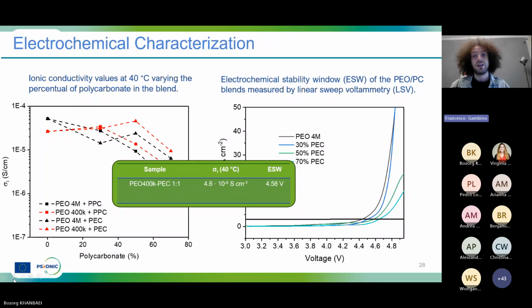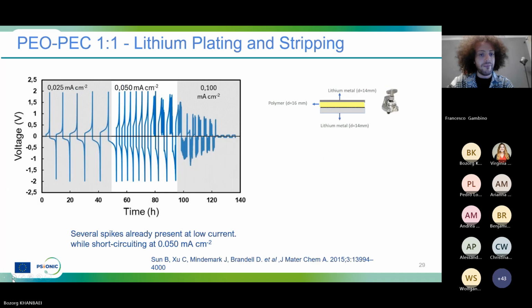At this point, we selected one membrane to further characterize, and in this case, we selected the one made of PEO 400,000 mixed with PEC in the ratio 1:1, because it displayed the best ionic conductivity among the series, and also the electrochemical stability was improved compared to the starting material. Next slide. We started the characterization of this membrane with lithium plating and stripping.